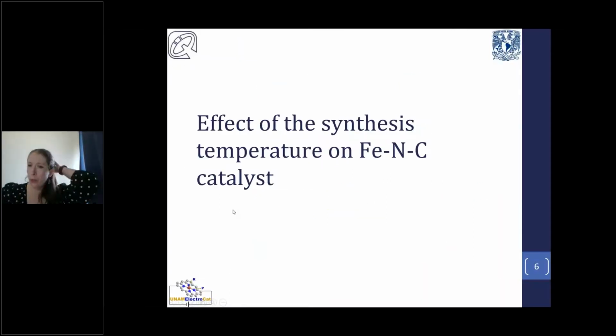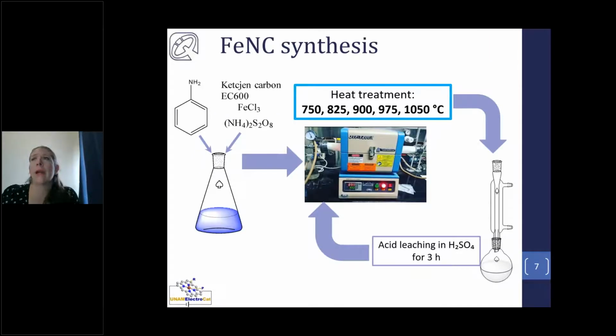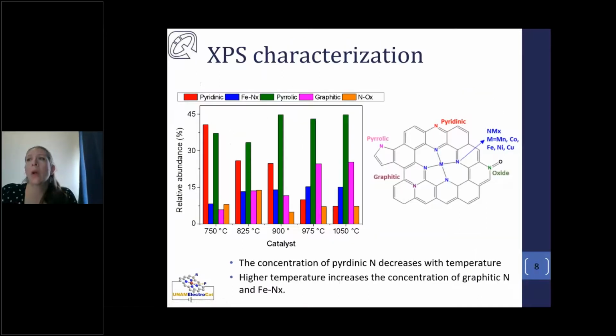So I started working on this class of materials when I came back to Mexico to work at UNAM. And the first thing we did is try some of these catalysts based on polyaniline, and we just change a little bit the structure of the material by changing the synthesis temperature. So we went from 750 degrees to 1050 degrees Celsius for the synthesis, and we characterize the resulting materials. What we observe is that the structure of the material changes a lot with the synthesis temperature.